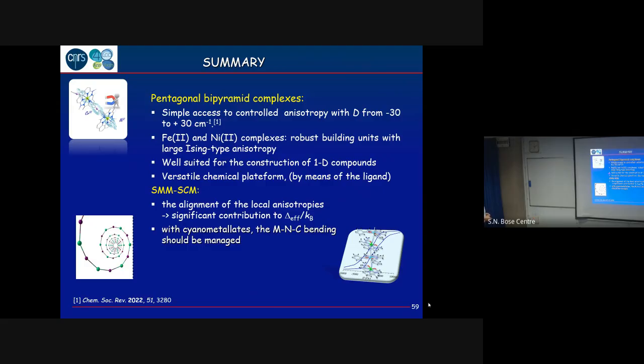These complexes are also well suited for the construction of 1D systems because you just exchange the apical positions. So this is a good situation to make a 1D system. And because of the ligand, it's also a very versatile platform to introduce other things like carbonate. The message about the construction of single molecule magnets and single chain magnets is that when you design this kind of system, it is very important to align the magnetic moments, because it has a very significant contribution to the energy barrier. And also, when you use a cyanometalate, the bending of the coordination bond can also be important.